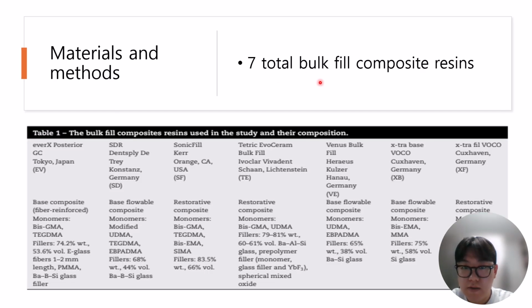A total of 7 bulk-fill composite resins were tested. They can be divided into two categories. First, the flowable type. These are low viscosity materials that require a top capping layer. First example, SDR, SD, very flowable with high conversion but lower strength. Second example, Venus Bulk Fill, VE, has the lowest filler content, making it less strong. Extra Base, XB, is the strongest among the flowables due to its higher filler content.